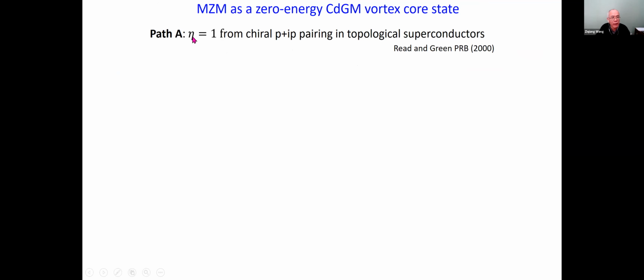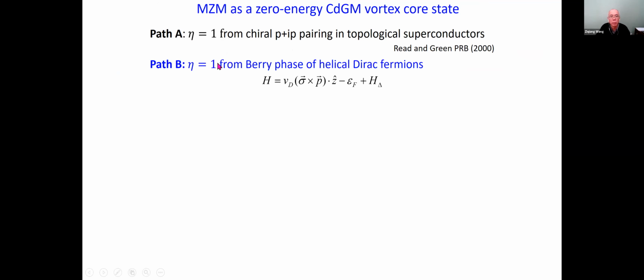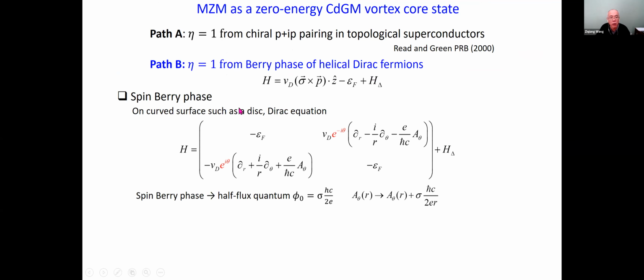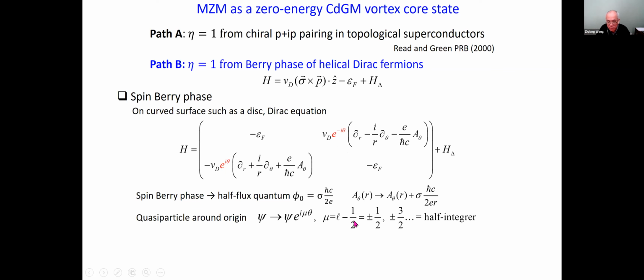The path B is to get this eta not from the pairs, but from the particle-hole sector, that is through the Berry phase of the helical Dirac fermions. So if I write the Dirac equation on curved space, such as I take a disk, you see there is this phase, this wonderful phase factor coming out, and that's the spin-Berry phase. And that adds this half angular momentum in each of the spin species. So even in the normal state, now, if I take a particle going around the origin, I would pick up